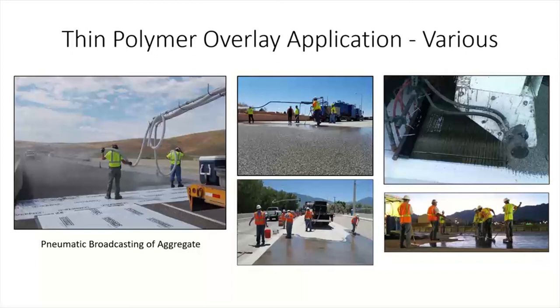If you're going to walk on the resin, have spiked shoes. If you're going to walk on the aggregate, don't twist your feet around and things like that. So it's always perfect not to walk on the resin or the aggregate if you can do it. And there's ways to do that. The top right photo, you can see it's being done in an automated method. The truck was driving down, spreading the resin binder and dropping the aggregate, and the whole thing was pretty much fully automated. And that's another consideration as well.